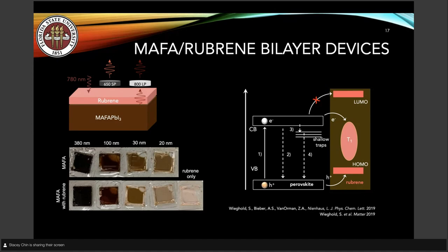It's a common upconverter. Here, top left, you can see the general device structure. The idea is that upon 780 nanometer excitation, you get either emission from the perovskite, or you can see the upconverted light emitted around 600 nanometers. And on the bottom left, you can see our devices. So we went into the thickness dependence of the upconversion, and we saw that roughly 100 nanometer thick film is actually the best. There's a trade-off between efficiency and reabsorption here.